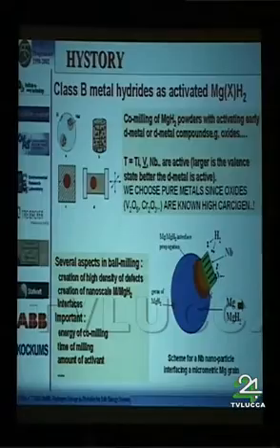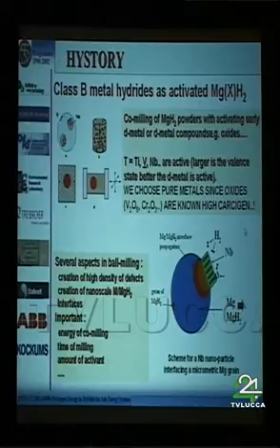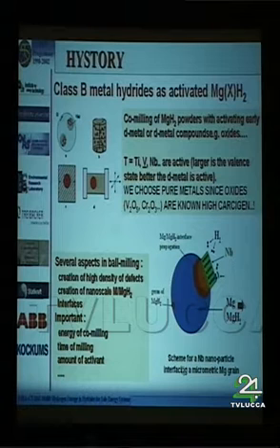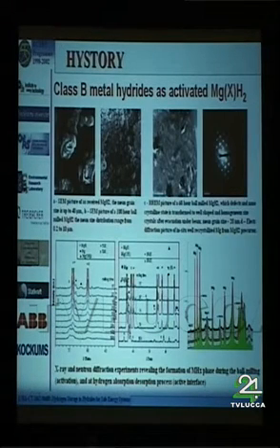and so we aim also during this work to get a more fundamental insight about how works the interface between the catalyst, for example, niobium and vanadium, and the magnesium grain. This interface is very, very sensitive and very important in terms of very high kinetics of charge and discharge.